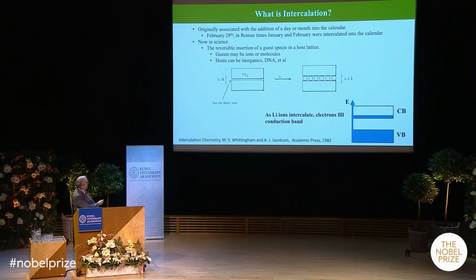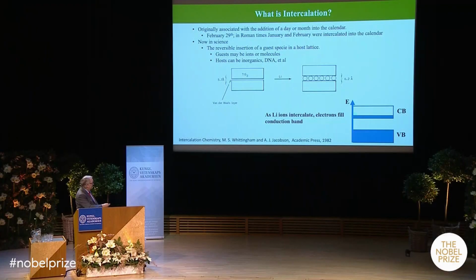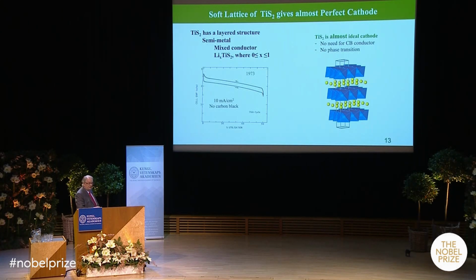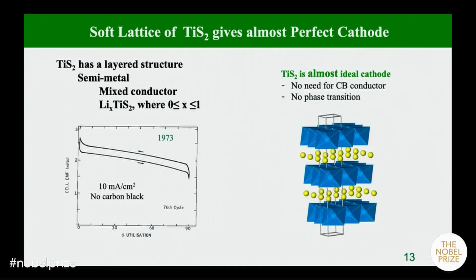But we've got a layered structure like TiS2. If you look at this, it's about 5.7 angstroms. You put lithium in, it expands by half an angstrom. So these are the ions going in here, and then you've got the electronic structure. The valence band is full, so the electrons then start filling into the conduction band. Clearly, as you fill this up, then the voltage you're going to get out of the cell drops somewhat. But there are some key aspects of this material that I want to show you. Here's TiS2. It has a layered structure exactly like this, exactly the same as cobalt oxide.